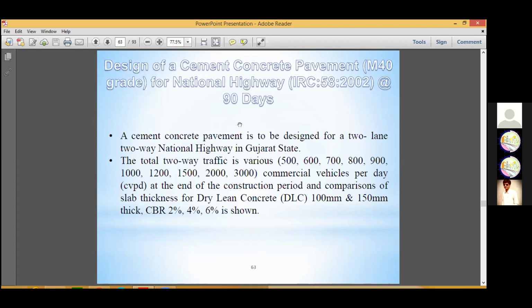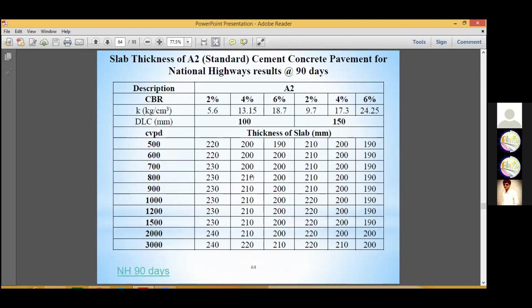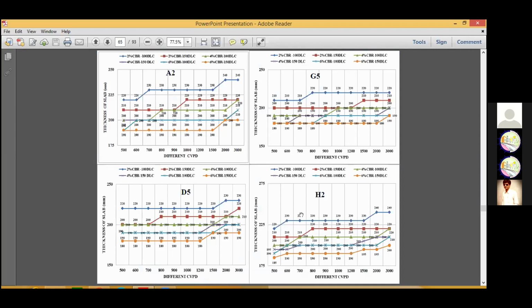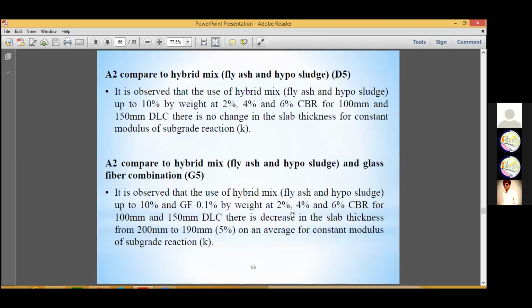But now, up to here, in this particular work, we go up to 90 days and we check. So here, the same A2, you refer to this table. I completed all of this with A2, B1, B2, B3, B4, C1, C2, C3, C4, D1, D2, D3, D4, and many more, around 52 types of concrete, tested and analyzed in rural roads and in national highways at 28 days, 90 days and 360 days. So here also, a 190 to 240 mm thick slab, and we refer to the same pattern in this particular work. The D5 and G5, here the 5% decreases, 200 to 190.